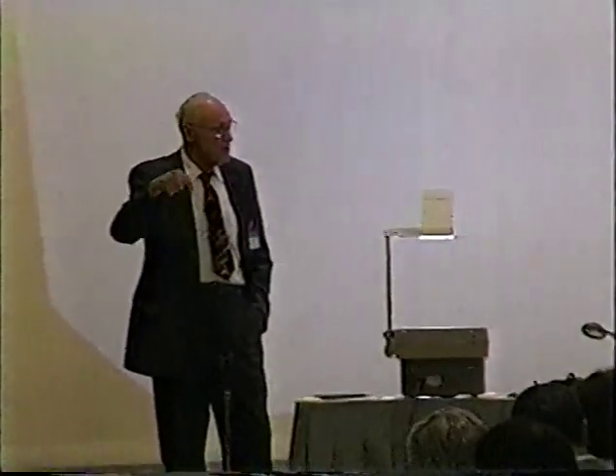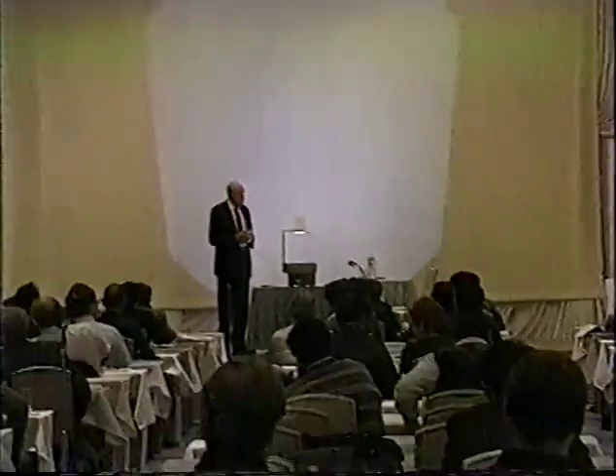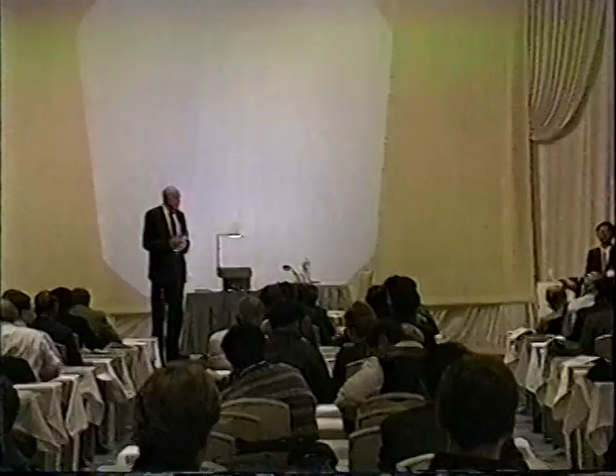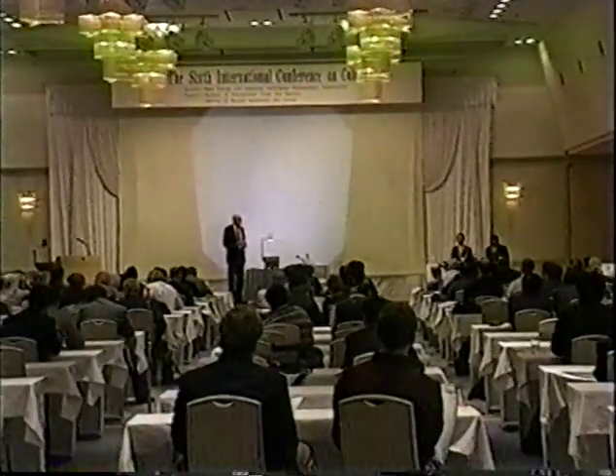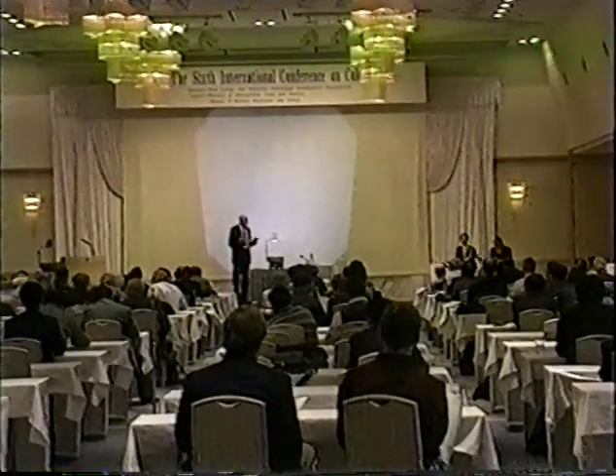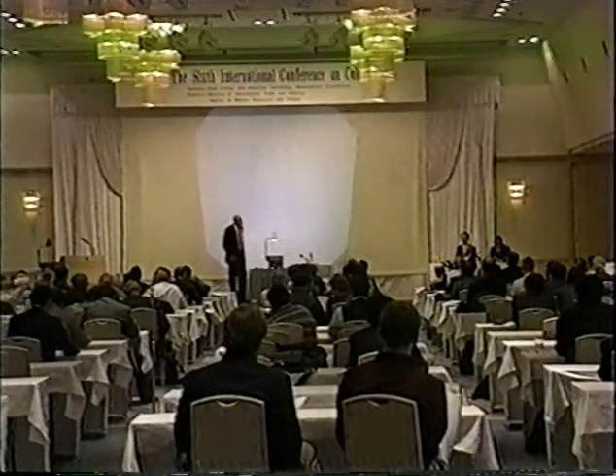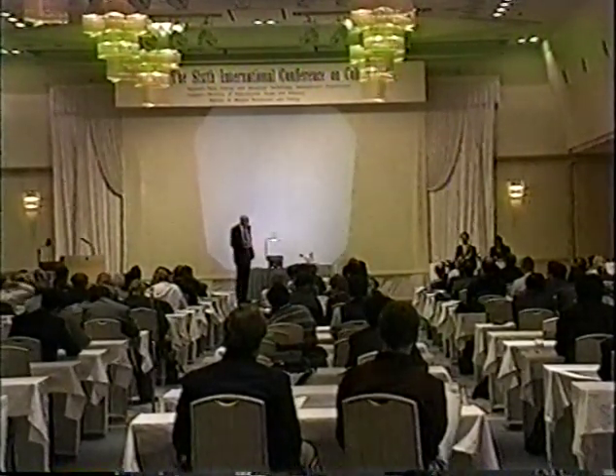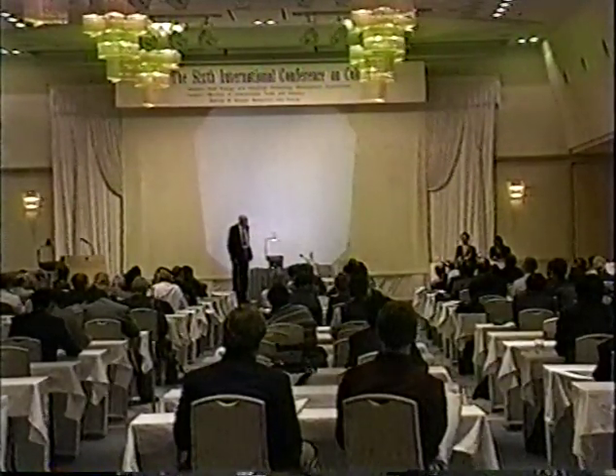Well, the beautiful thing about this system is that it is not subject to the problems that the SIMS has, time-of-flight SIMS and the SIMS, because it's looking at a tiny little spot on the surface. And you might need the entire GNP of the country to fully characterize every spot on the surface of a cathode, and also versus depth. So this method sees throughout the sample every atom that's present without worrying about whether it's representative or not. So I think it's more likely to be robust, but I admit that probably suggestive changes in palladium isotopes have been seen, and maybe I will eventually see that when I finally analyze about 40 or 50 gamma rays and get their ratios. But I haven't done that yet. I just got this data Monday before I got off to this meeting, and so I have a lot of work to do. Thanks for the suggestion.